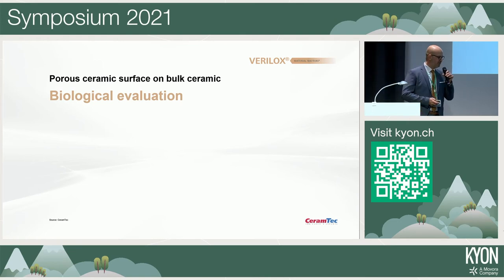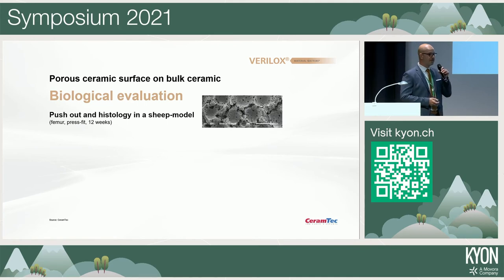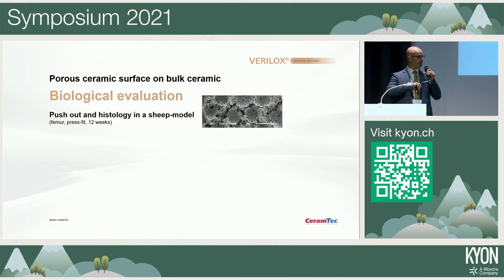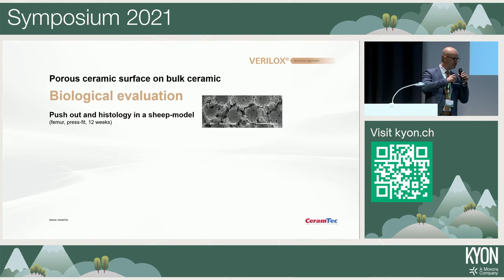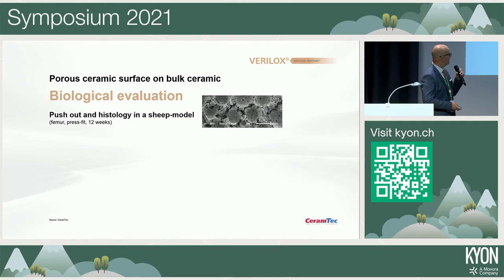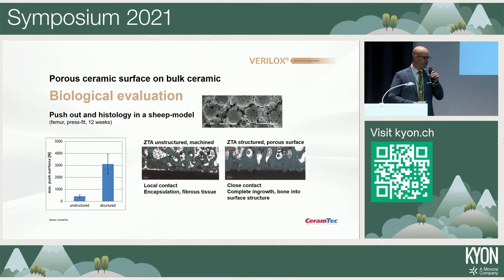And I have two studies for you today, and I want to show you the results. The first one was for a bulk material with a porous coating on top. So the first version I mentioned before, put into sheep in two versions, a smooth one and a coated one with pores. And of course, what we have seen here is the smooth one doesn't show any proper bone contact. You get fibrous tissue in between, while the porous structure got a perfect bone contact. And the respective push-out forces with regards to the secondary fixation.